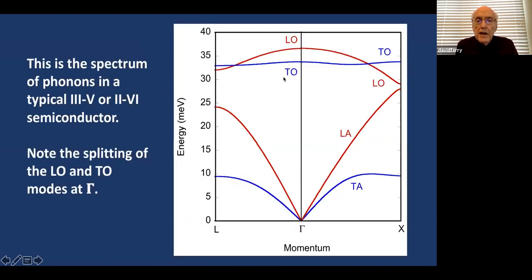Now, if we look at the spectrum, this is the spectrum for indium phosphide. Actually, it's for any 3-5 semiconductors, but it's drawn for indium phosphide. This is the optical branch. This is also an optical branch. This is in plane motion, longitudinal. These are the two transverse, because you have 3 dimensions in the crystal. So the two transverse are doubly degenerate. Okay, these are the acoustic branches. And these are the transverse acoustic.